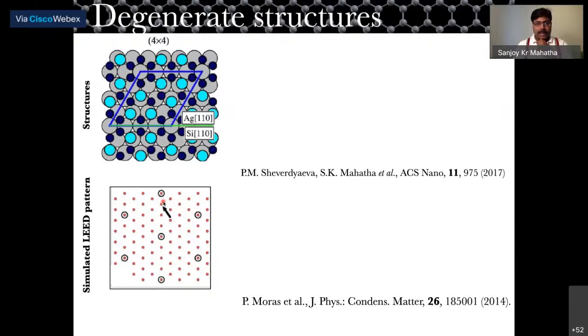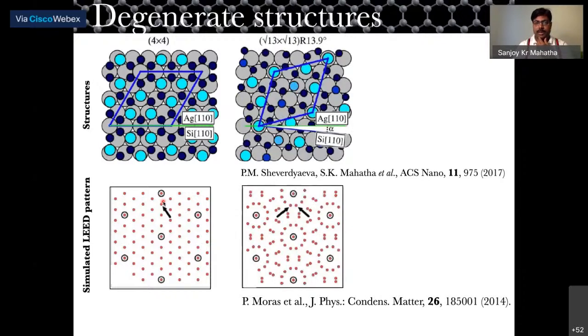Okay, but then the silicene networks can be rotated by 13.9 degrees, and the structure is called root 13 by root 13 rotated by 13.9 degrees with respect to the silver 110 axis. In this case, the simulated LEED pattern gives you this kind of spots, and these are the root 13 by root 13 spots. Then it has another structure, which is called 2 root 3 by 2 root 3.